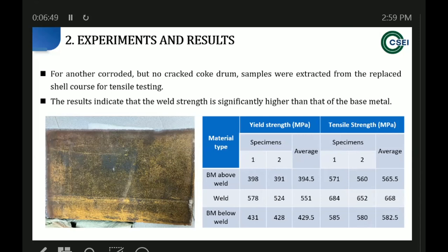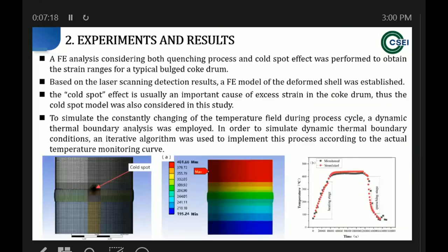So from these cases, we can conclude that the higher strength of the welding material may be important to help resist cracking, and that the stress concentration due to corrosion, the change of thickness, and the deformation of the bulging will promote the cracking initiation.